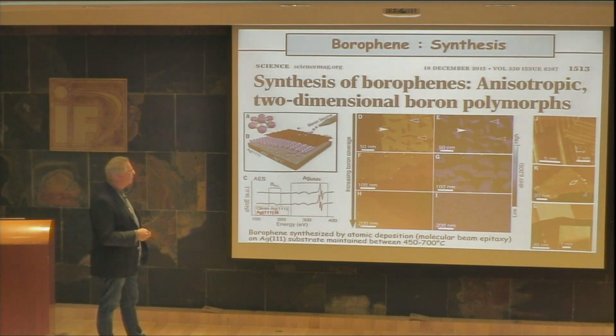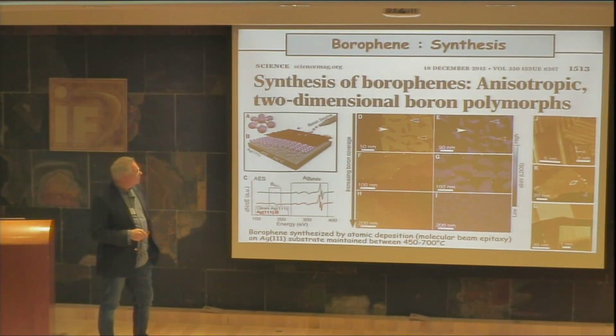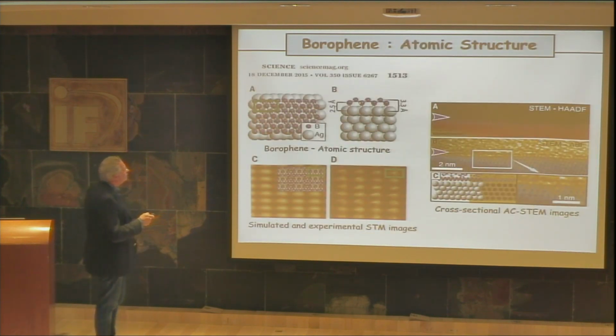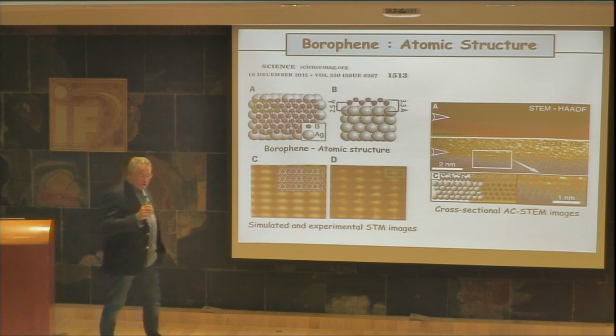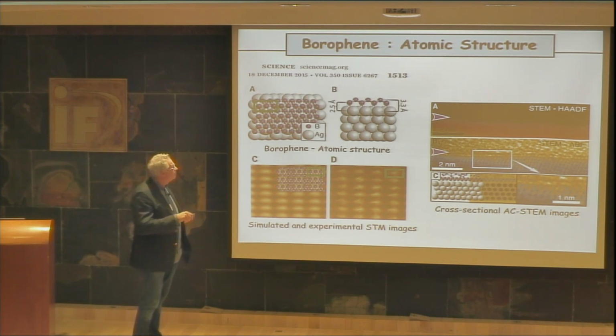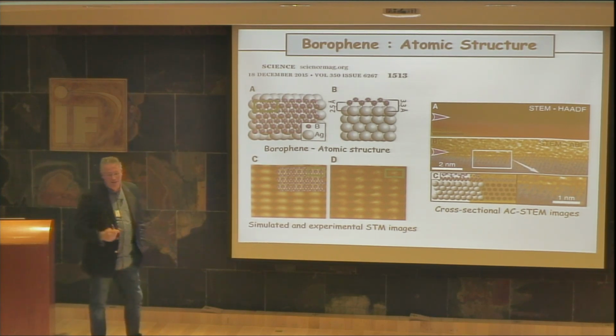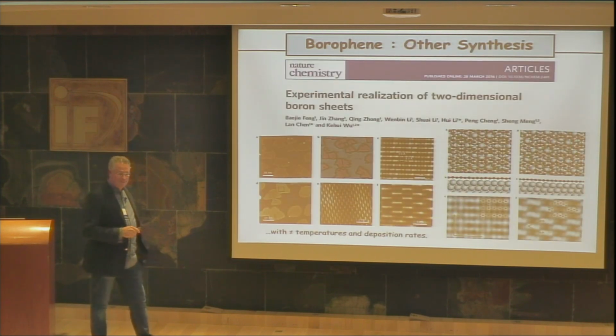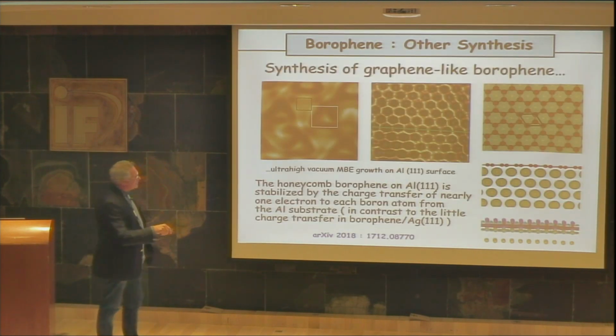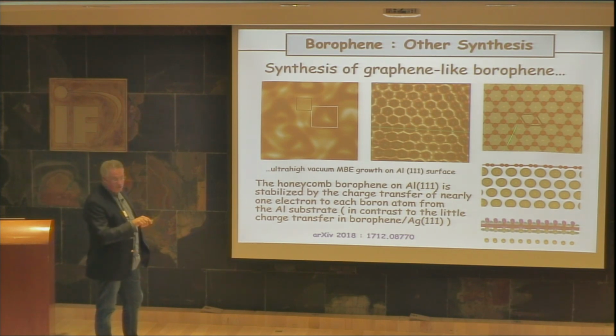Or the hexagonal one. In this case, the size of the crystals is close to 50 nanometers, especially in the case of the triangular lattice. And in fact, you have a close interaction of your borophene layers with the silver substrate. This is why you could probably stabilize these 2D materials, and in that way you could orient it. You have exactly the same in the case of aluminium, with this hexagonal phase of boron, and also a very strong interaction with the substrate.